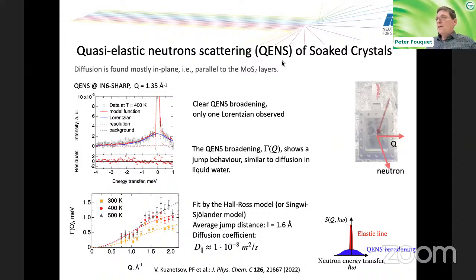And when we look at the neutron scattering, what we did there is we went to a time of flight spectrometer, and we looked at the broadening of this elastic line. That's what's called quasi-elastic neutron scattering, and that tells you something about the diffusion. Meaning that when the particles, in our case the hydrogen atoms or the water, move in the sample, then the elastic line will be broadened, and you will see a slight foot here that's typically following a Lorentzian broadening. And we saw such a broadening, so we saw some motion. And the analysis showed that this pretty much can be modeled by the diffusion of liquid water. So it's just the physics of water in cracks that we see.